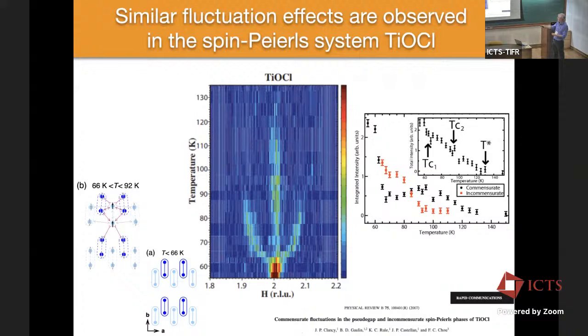Then there's an intermediate state that is actually incommensurate. All of this was seen in high-resolution X-ray scattering at almost the same time that we published this paper. But our measurements also showed this streak of commensurate fluctuations that goes up to double the temperature at which you see the long-range order commensurate structure formed, okay? The interesting thing is that if you look at the temperature dependence of any one of these features individually, like this commensurate feature here, or these incommensurate features here, each one of them individually has quite strong temperature dependence.